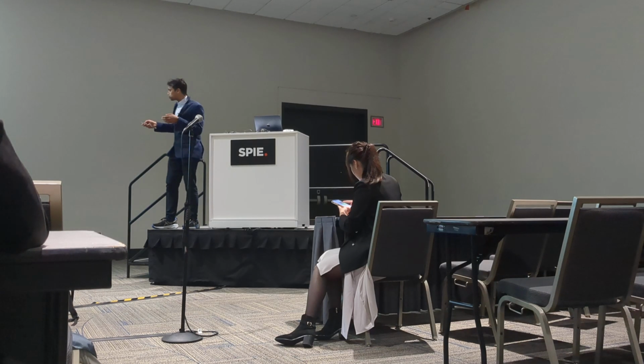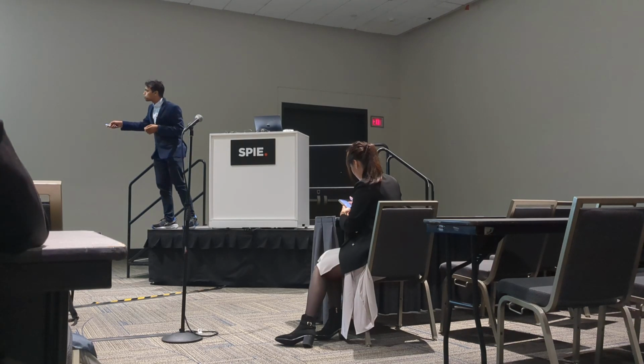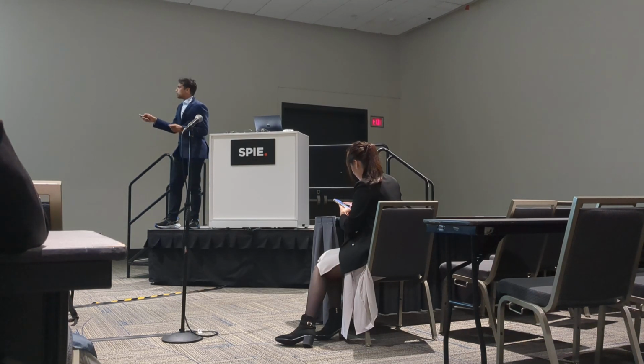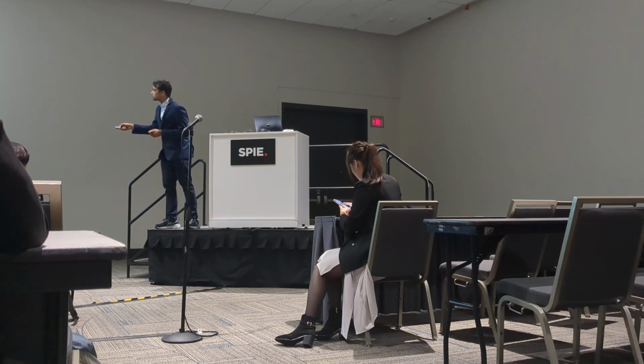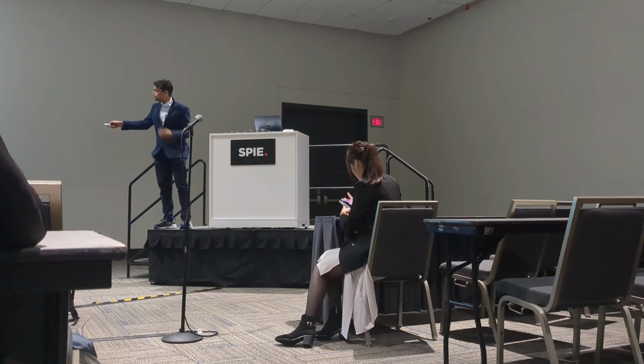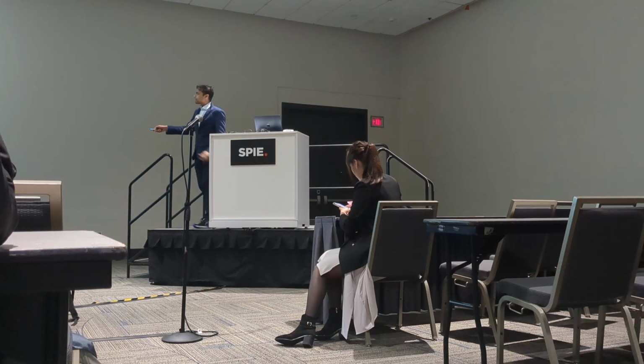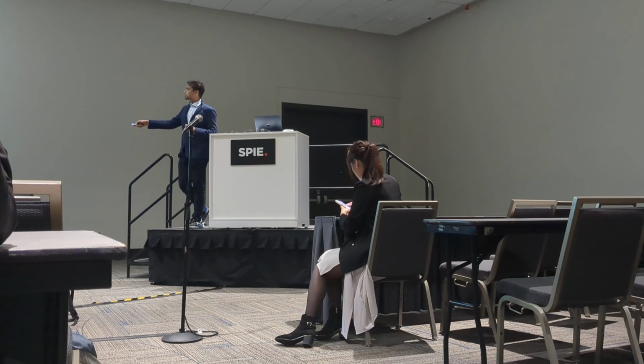From the cross-section view, what we observe is that these gallium droplets are embedded into the substrate. Not only that, we have a very drastic size distribution based on this PDMS ratio, which means there is different PDMS or oligomer content. So based on oligomer content, we see this different distribution. But as we remove the oligomers, the size distribution becomes almost the same and the color becomes very blank.